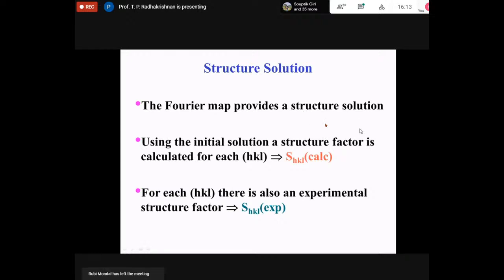And in real crystallography, you go through what is called a refinement process. These steps are very briefly mentioned here. You take the structure factor data, do a Fourier synthesis, and create a Fourier map, which is called the structure solution, which roughly tells you where the electron densities corresponding to different atoms are. That initial solution you use to calculate a structure factor. That means you now roughly know where the carbon and nitrogen and oxygen atoms are. So you know the position of the atom, you know the type of atom, but you may not be very sure because carbon and nitrogen are so close in atomic number, you may mix up between the two. Because in the real experiment, you get only electron density. If it comes out to be 6.2 electron density, then it could be carbon or it could be nitrogen with a lot of disorder, for example.